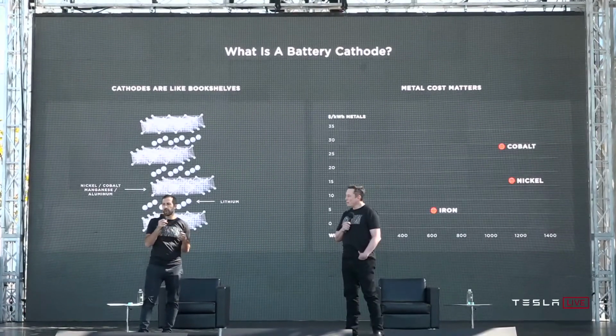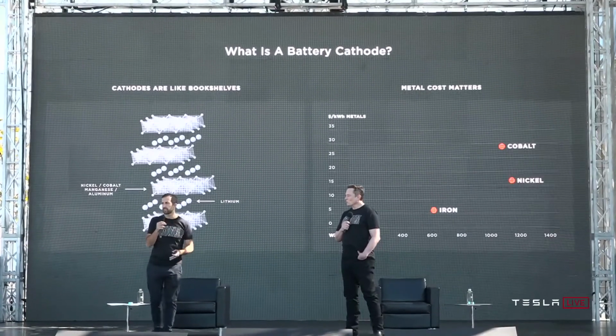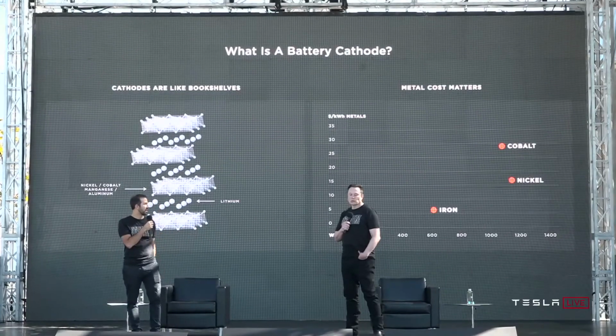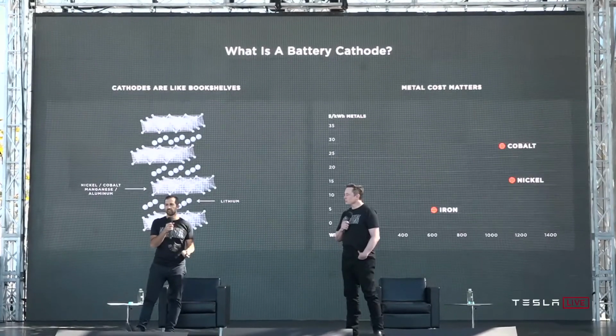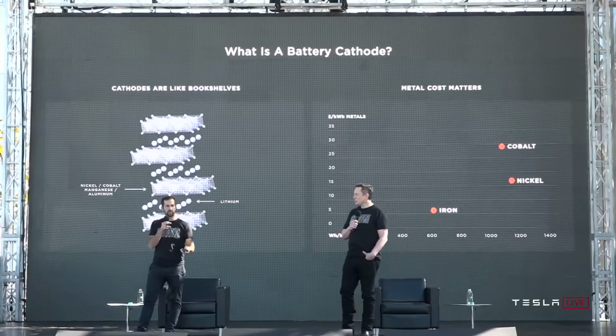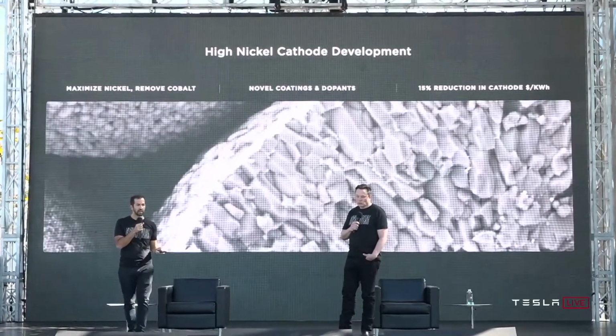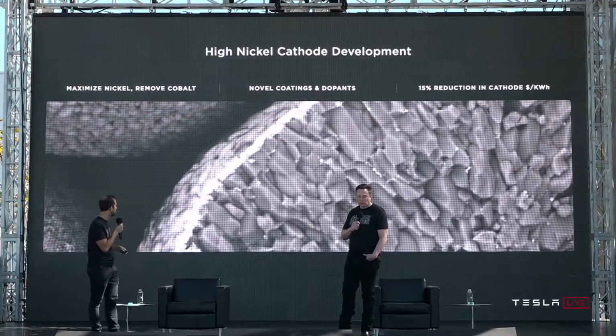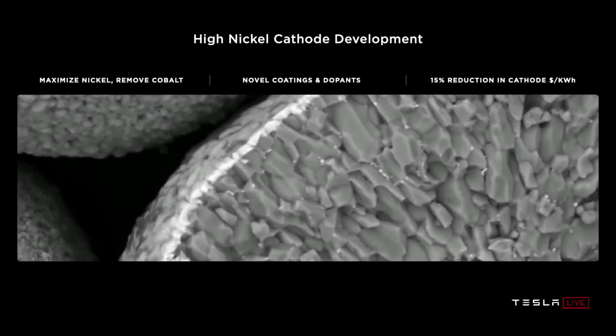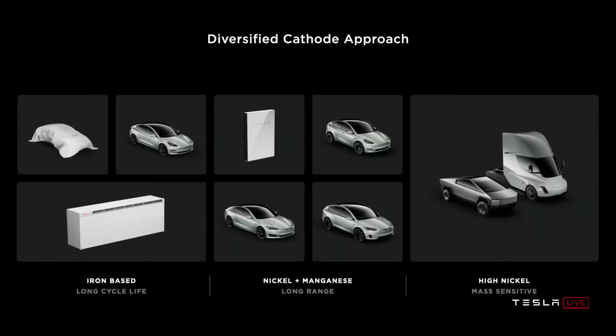But one of the reasons why cobalt is even used at all is because it is a very stable bookshelf, and the challenge with going to pure nickel is stabilizing that bookshelf with only nickel. And that's what we've been working on with our high nickel cathode development, which has 0 cobalt in it. Leveraging novel coatings and dopants, we can get a 15% reduction in cathode dollar per kilowatt hour. It's a big deal. But it's not just about nickel.